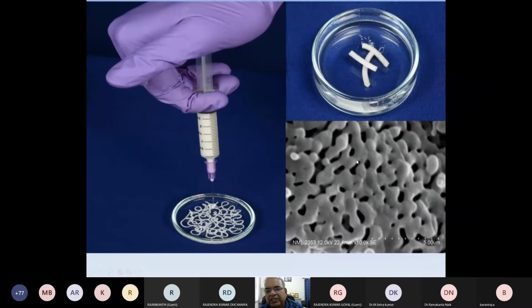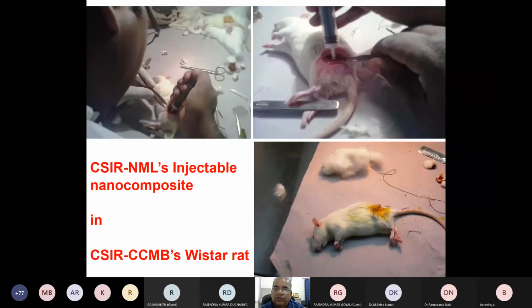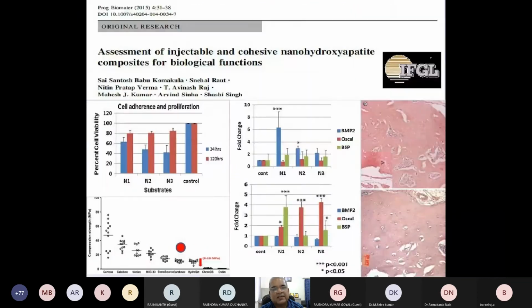We looked at the microstructure, which was highly porous, which is a requirement for a bone graft for cell interaction. Again, with the help of CCMB, we did the animal test, published a paper on the bioactivity of our paste, and we determined its mechanical properties. Its mechanical property was quite good, even better than the internationally available product. And this know-how was taken by another industry, IFGL. It's a well-known ceramic and refractory industry in Eastern India.